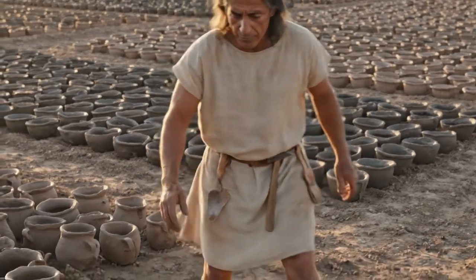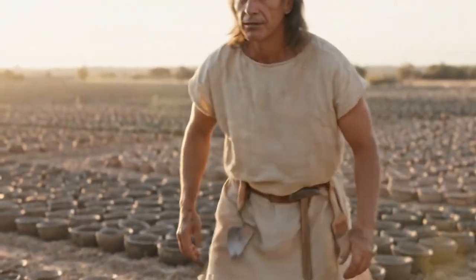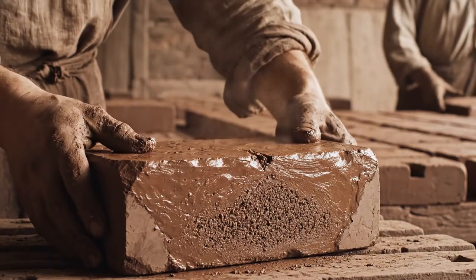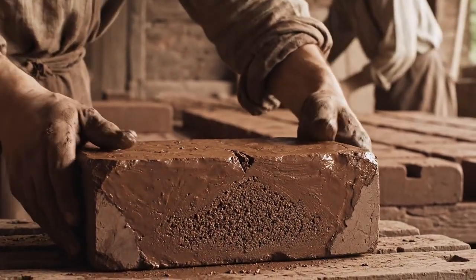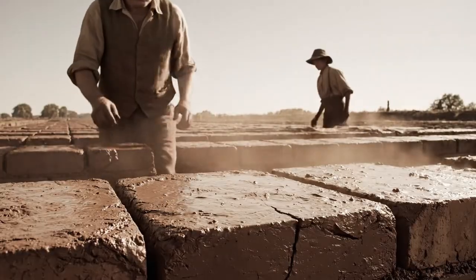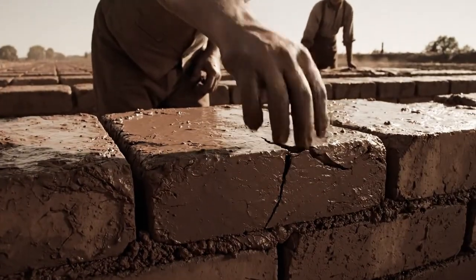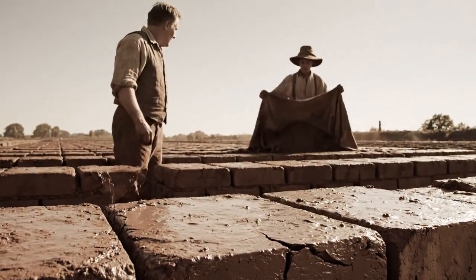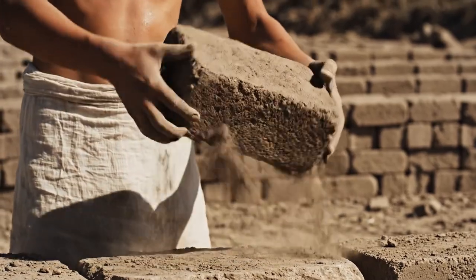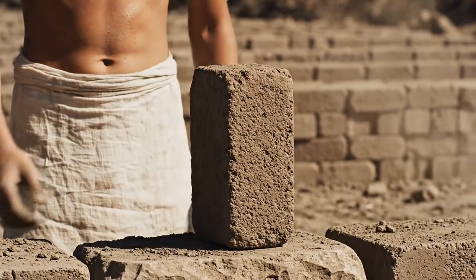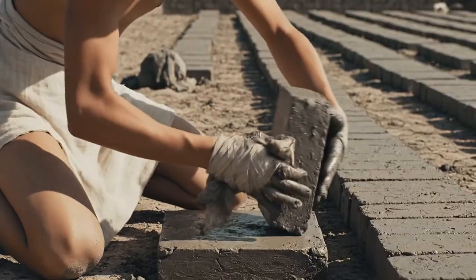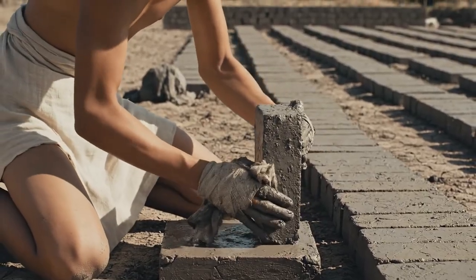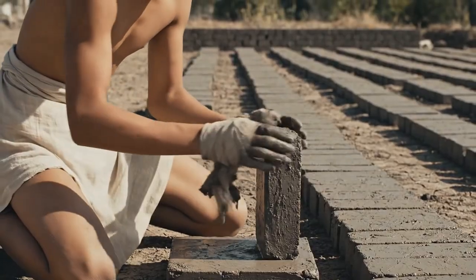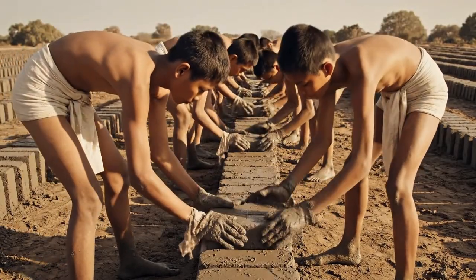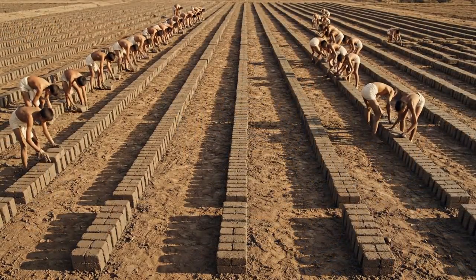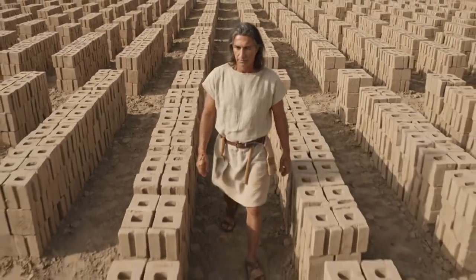Now comes the most critical and most vulnerable phase of the entire process, and it's the step where most failures occur if you don't understand the science of clay. Drying. Watch what happens to these freshly molded bricks because they look solid, but they're actually about 25% water by weight. And all that water needs to evaporate slowly and evenly, or the brick will crack, warp, or crumble into dust. The bricks are being left exactly where they were molded for about 4 hours, just long enough for the surface to firm up enough that they can be handled without deforming, and workers wearing wet cloth wrapped around their hands to keep the bricks from sticking to their skin are carefully standing each brick on edge, tilting it at a slight angle to allow air circulation on all surfaces.